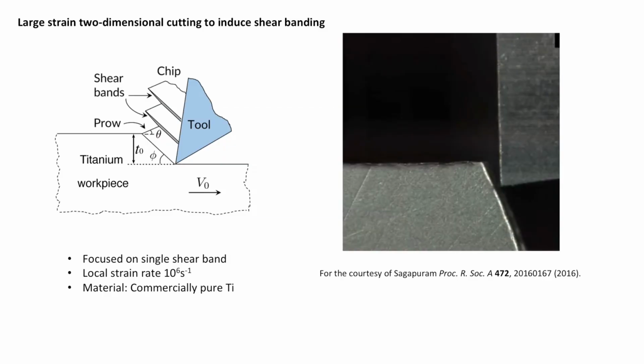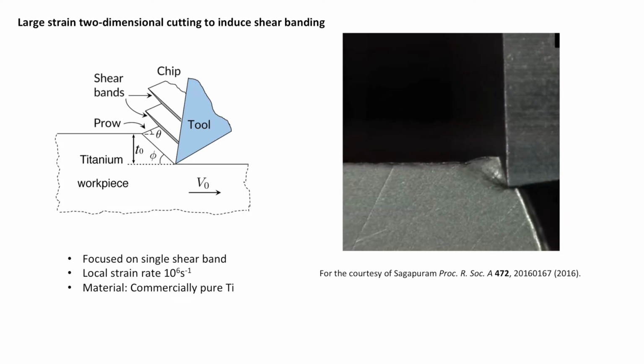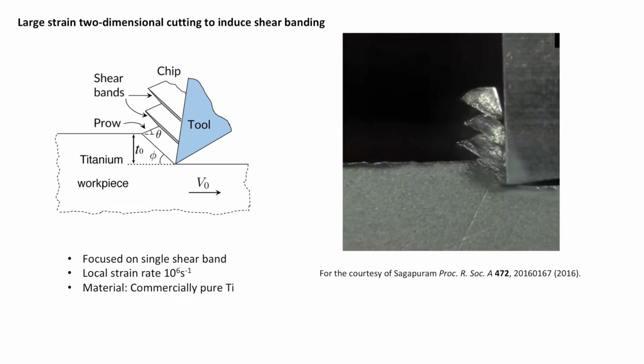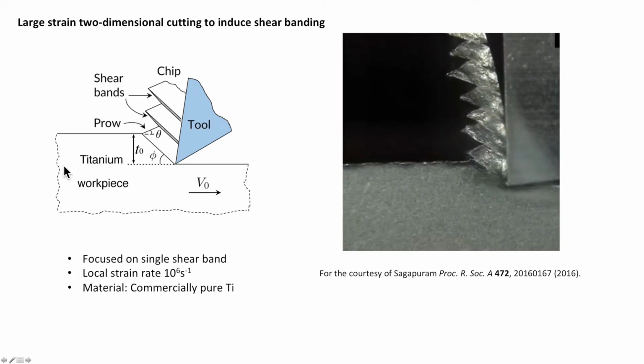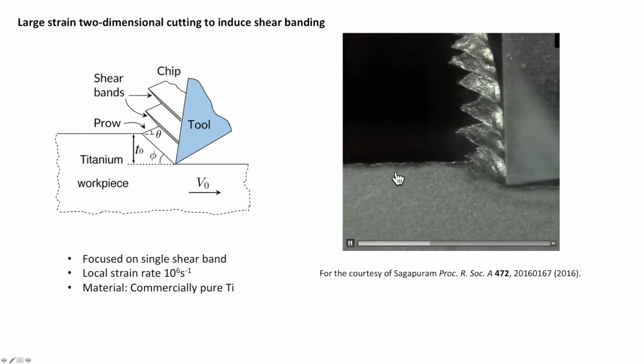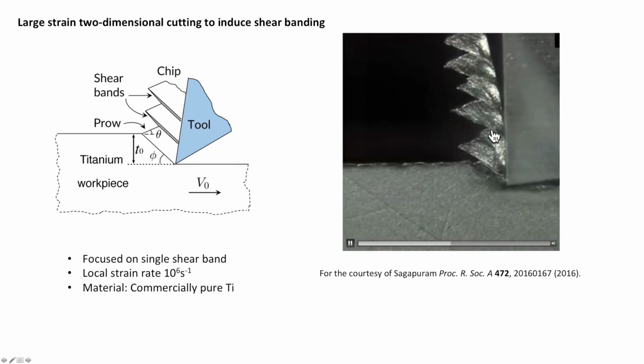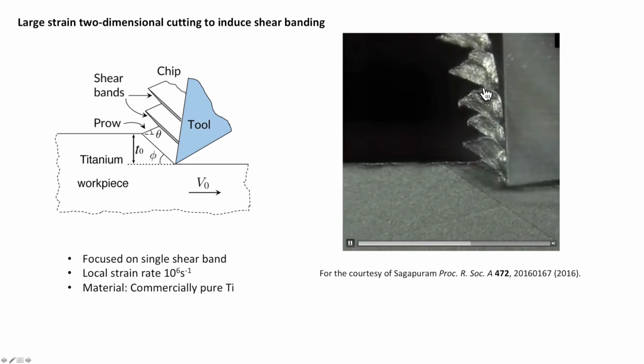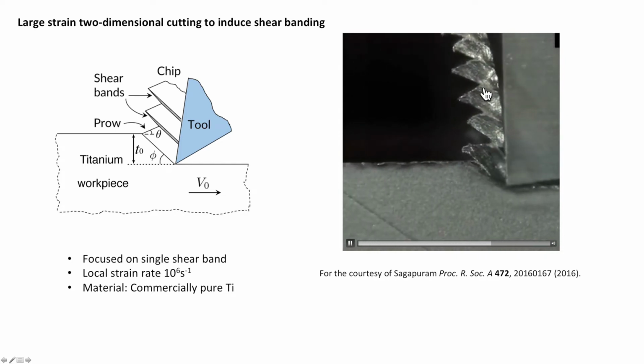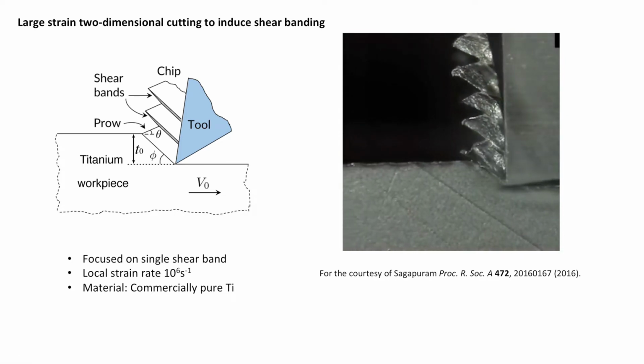To answer the question, we collaborated with Professor Dinaka Sagapuram's group, who specialize in cutting. Here is the experimental setup. You have the blade here, and as you feed material towards the blade, a metal strip can form. One special feature about titanium is that when you cut it, instead of forming a smooth metal strip, you get this serration.